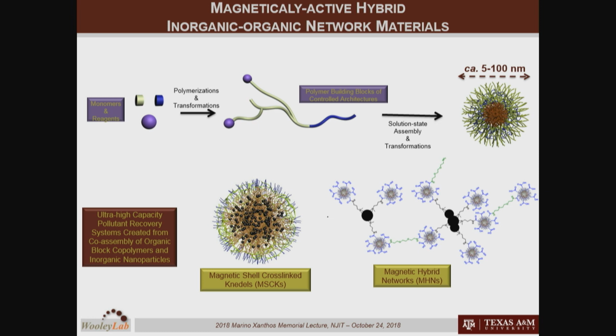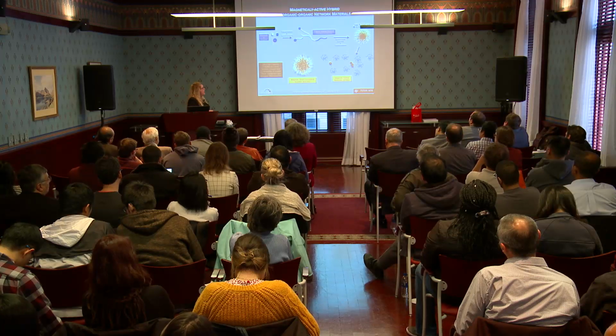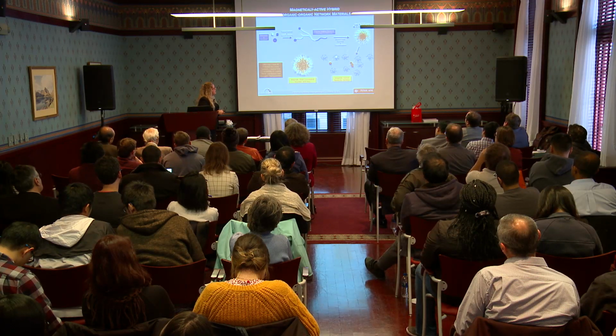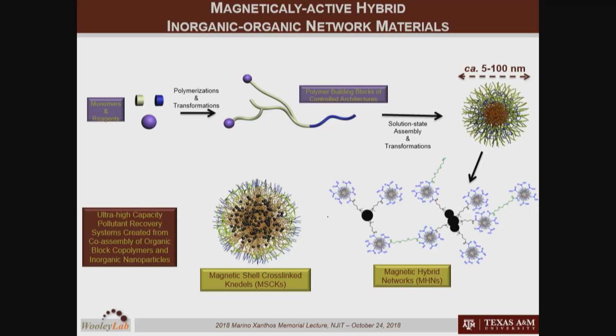And that particle then can be coupled onto the inorganic particles. And as I'll show you, we initially just wanted to have a central inorganic particle onto which was coupled organic particles. And what we found instead was that there were multiple coupling reactions occurring between not only the organic particles onto the inorganic, but also the organic particles to the organic particles. And that's what creates this network-like structure.